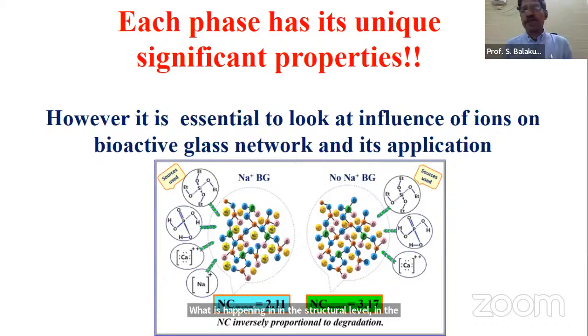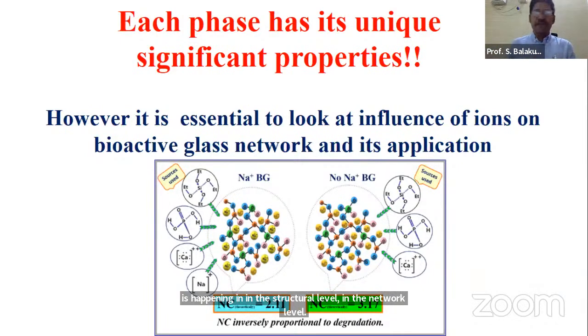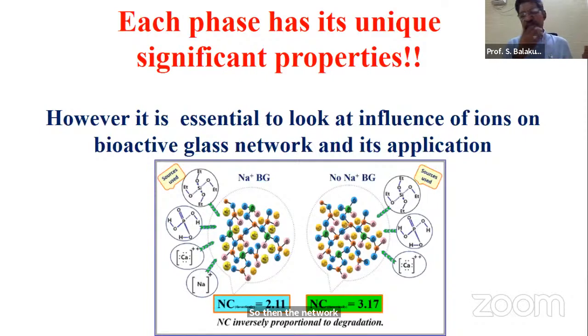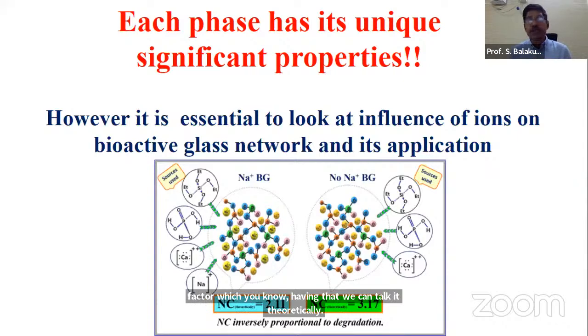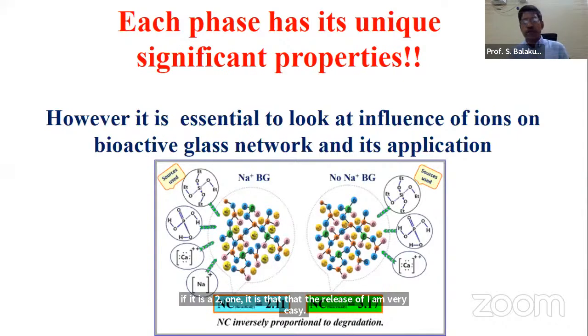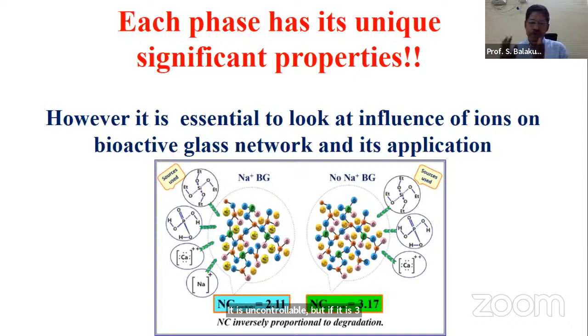At the network level, obviously, it is good if it is above 3. We found that network connectivity is a factor which you can calculate theoretically. If it is 2.1, the release of ions is very easy. It is uncontrollable. But if it is 3.1, if it is above 2.5, you can control it. If it is around 3, you can definitely have very good control and release it.